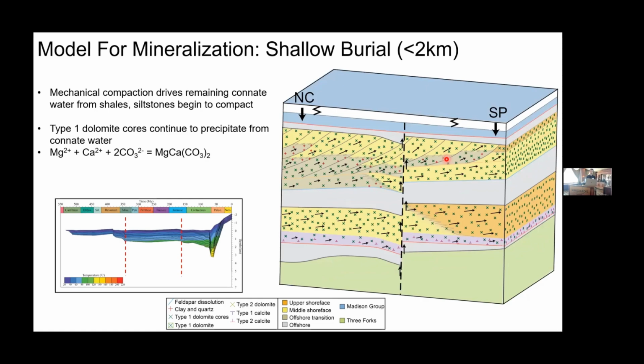The next phase was shallow burial. So this is generally that time frame that I mentioned earlier. After the Mississippian, we had that long period of tectonic quiescence where the Sappington was about 70 degrees Celsius and stayed that way for about 100 million years. During this time, the mechanical compaction would have driven the remaining connate water from the shales, and eventually the siltstones themselves would begin to compact. And from that, the type 1 dolomite cores continued to precipitate from that connate water.